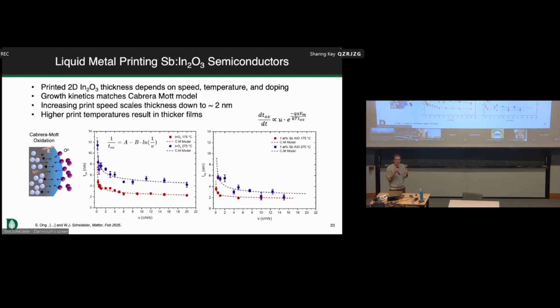One, it tends to grow the same thickness everywhere. It doesn't really matter if we do it on a large scale, tens or hundreds of square centimeters, or a really small scale. So it tells us that it's really the kinetics of that Cabrera-Mott process that are governing everything. We can control it with temperature. As you might expect, it's thermally activated, so we're relying on a competition between the diffusion of the oxygen anions across that barrier. They have to burrow or diffuse their way through the metal oxide film. The reason it's fast at the initial growth stages is because of the electric field.